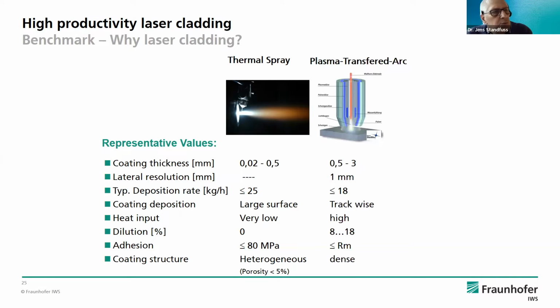Plasma transferred arc is another. This is also done trackwise. Different coating thicknesses are possible, but the heat input is quite high, and the dilution of the base material is up to 18%.